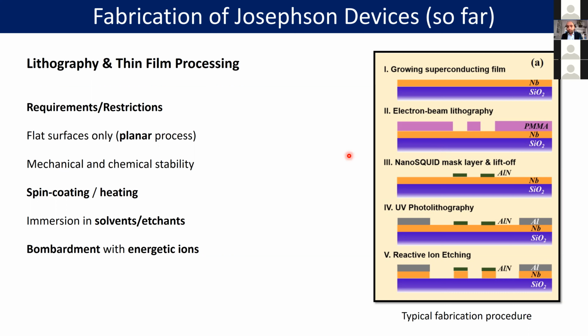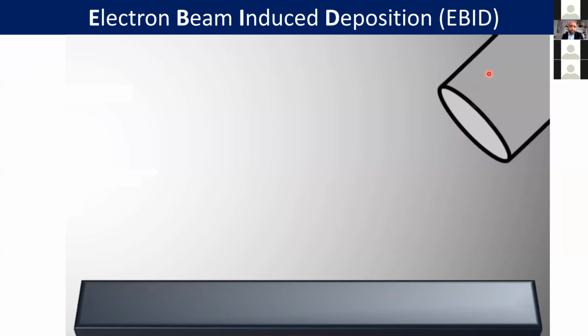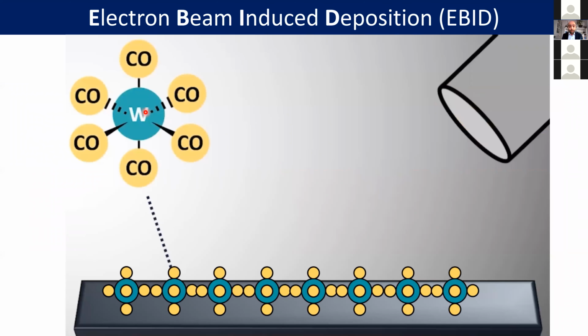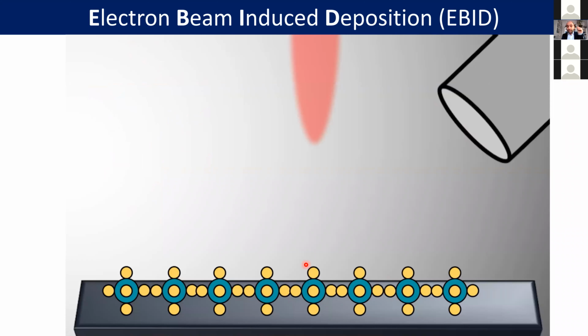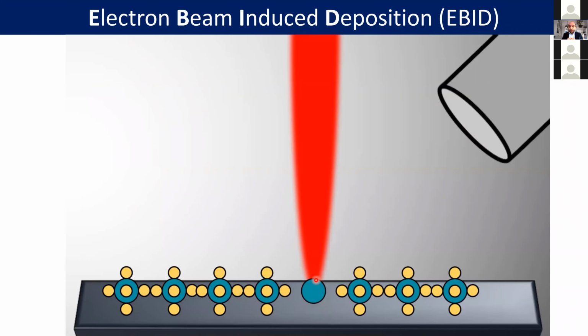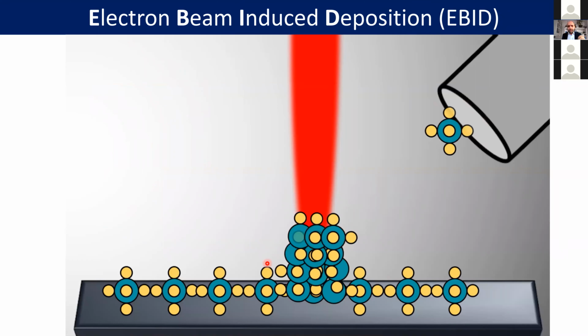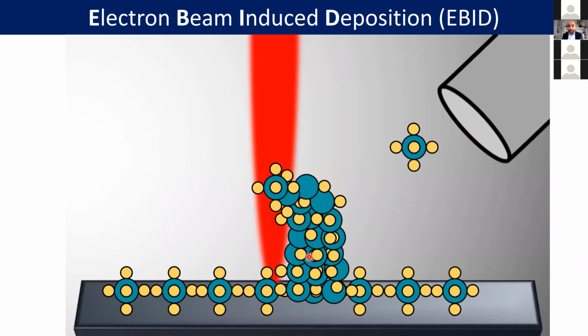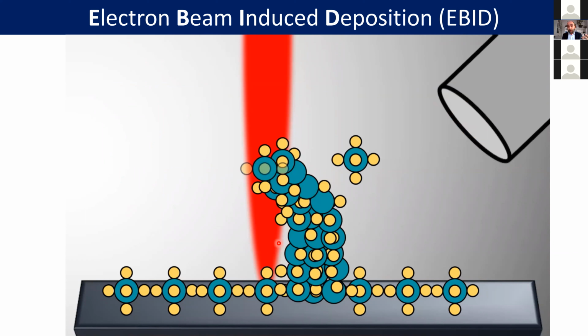What we wanted to do was to bypass all these processes using a direct write approach known as electron beam induced deposition, or EBID for short. Now, the way that EBID works is that you inject some form of precursor molecule, usually a metal organic compound, into the chamber of a scanning electron microscope. Now, these molecules are stable until you expose them to a focused electron beam, at which point they dissociate and form a deposit on the surface. And this deposit in our case would be tungsten carbide. Now, if you scan your beam carefully, you can make both 3D and 2D structures, both planar structures and 3D.